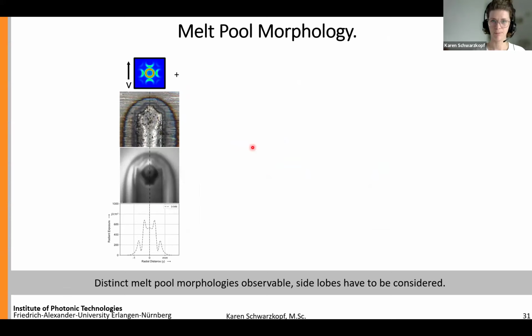Now, if we are switching to the melt pool morphology, which is also well known to influence microstructural appearances, it is interesting to see this for the ring. Basically, not only the main lobe, so basically this area here, but also the side lobe is incorporating the melt pool itself, which is highlighted here. And this molten zone is followed by a heat affected zone, as we can see in the cross-section analysis. And this heat affected zone again is followed by a tempered zone, as shown here by the blue tempering coloring. And this is the melt pool shape.